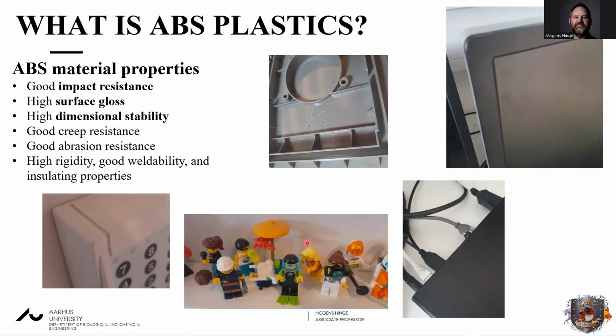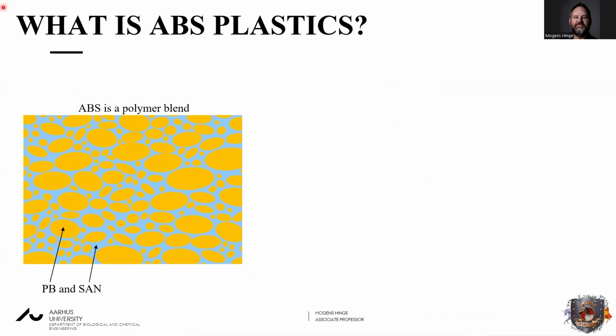The first reason is the impact resistance. So ABS has good impact resistance. It has a nice surface gloss, so you can see you get really wonderful surfaces. It is dimensionally stable, so it's having the same size day by day. Then another property is that it is creep resistant, it is abrasive resistant, so it doesn't scratch that easily. And then there are rigidity, good weldability, and insulating properties. But the main reason for choosing ABS is the impact resistance, the surface gloss, the high dimensionality, and the easy processability. So let's dig a little bit deeper into what is ABS.